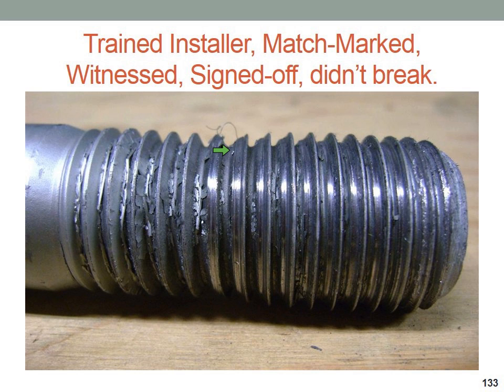But in reality, we've already lost to partial stripping these first couple of threads. Actually, a better way to look at it is this would be the depth of engagement for the nut if it were still installed. Essentially stripped the first thread and a half, haven't done much damage to the threads farthest from the grip. But we're seeing a lot of galvanized fasteners with really effective lubricants being installed to that condition.